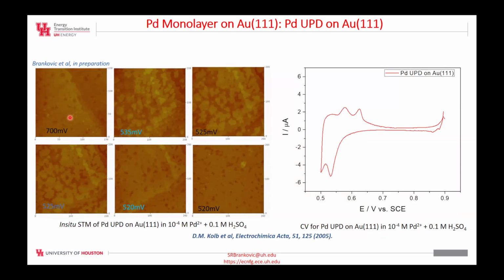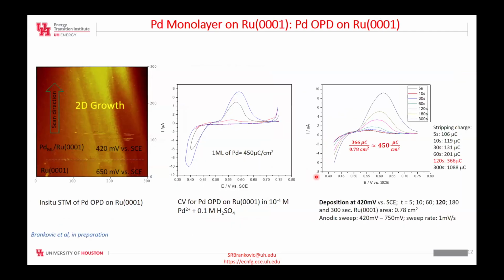You can see here an ultra pure clean gold surface, through the process of electrochemical deposition, is actually decorated with exactly a monolayer of palladium, which corresponds to this peak here where the palladium deposition is accomplished. So therefore, we don't have to do too much to create this ideal catalyst for hydrogen isotope separation. In the case of ruthenium, where we want to demonstrate the opposite effect of the compressive stress, the lucky thing is also that palladium grows 2D on ruthenium, and basically what we need to do is control the charge passed, which corresponds to about a monolayer of palladium, and then stop the process.